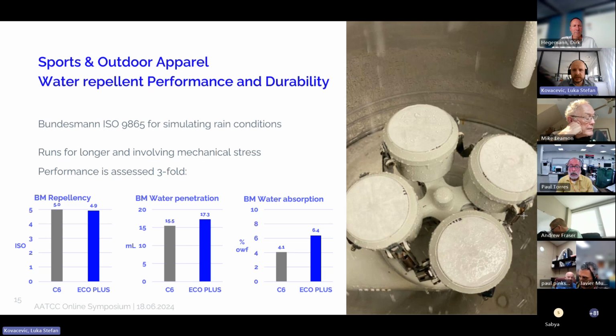Some customers want a more in-depth look at performance, and this is when the Bundesmann test comes into play. Here you have the fabric samples attached to these chambers, and the water drops fall from a greater height, so you have more impact on the fabric samples. There's a rotating metal frame or crossbar putting mechanical stress on the treated textiles from underneath, and you can also measure the penetration of the water that goes through the fabric. So you get three different performance parameters. One is repellency, similar to the spray test before, but you can also measure water penetration and water absorption of the fabric itself.